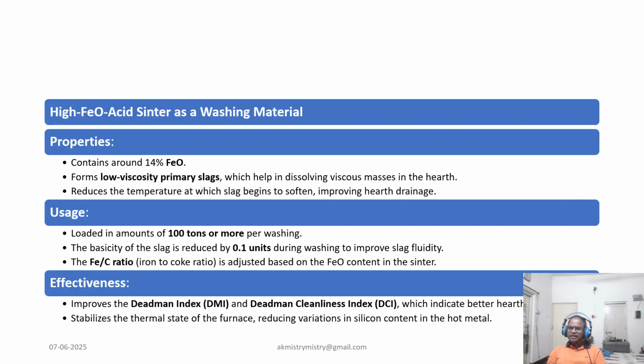So you can say high-FeO acid sinter. Let's focus on high-FeO acid sinter. What are its properties, uses, and its effectiveness? As for properties, containing around 14% FeO produces low viscosity slag that dissolves sticky hard masses, reduces slag softening